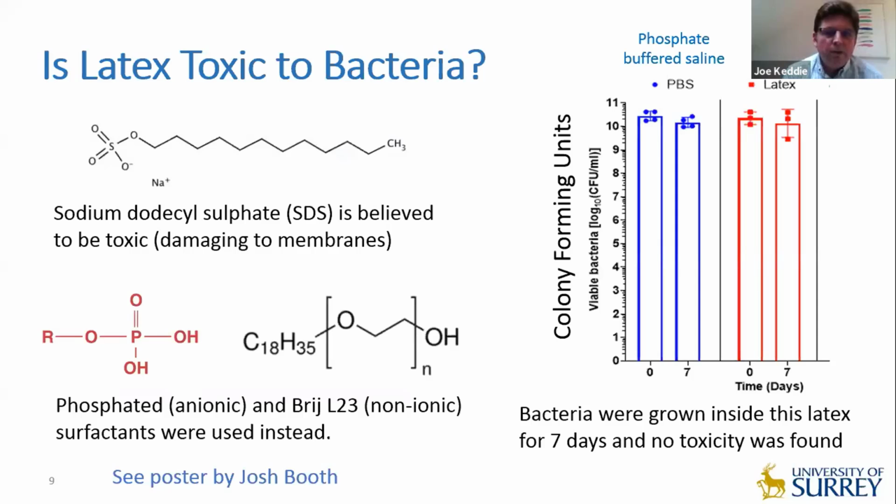And we did, with our collaborators, some toxicity studies. Here on the left, we're showing that the cell counts over 7 days are essentially stable if you put the cells in just a saline solution. And on the right, in the red bars, we're saying if you just add the cells to a latex and wait 7 days, the cell counts are virtually the same. So there is no sign of toxicity.